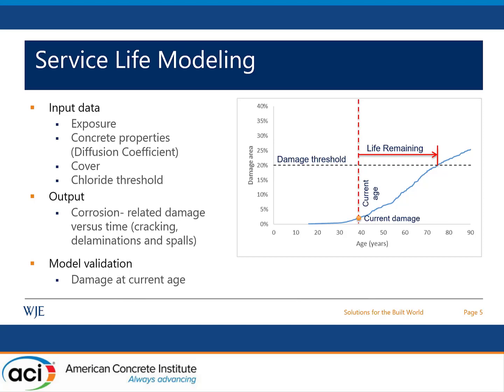And another input is the cover, and for this we use a specific distribution of the data that we collected from the structure. And chloride threshold, which is dependent on the type of reinforcement, also based on the mix design that we learn about usually from the petrographic examination of the core, or we also validate it based on the bar condition that we determine from visual inspection of the bars, whether collected in the cores or through an inspection opening.